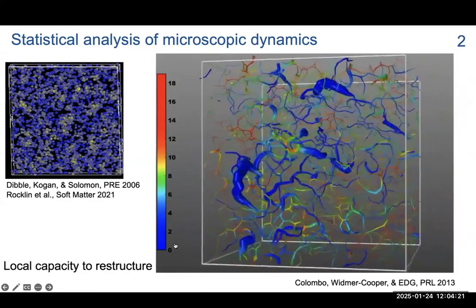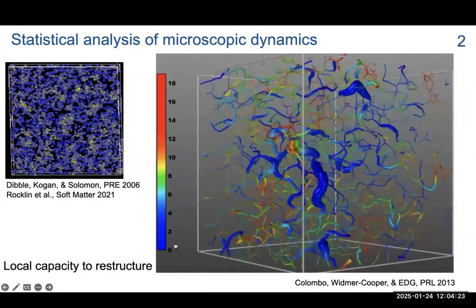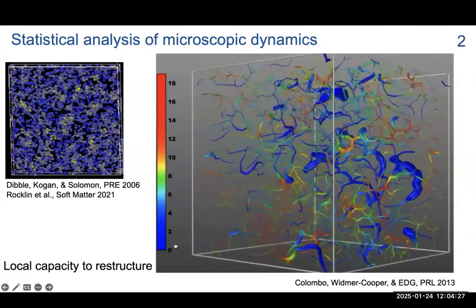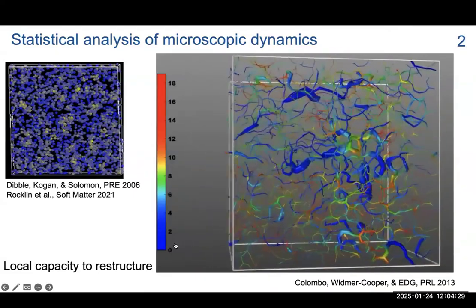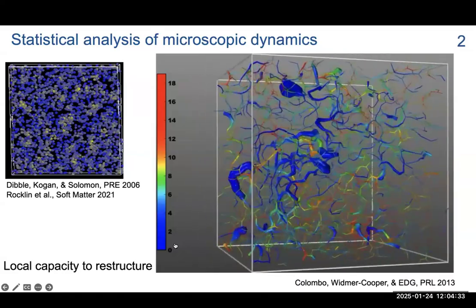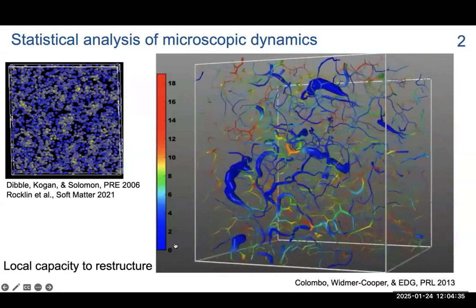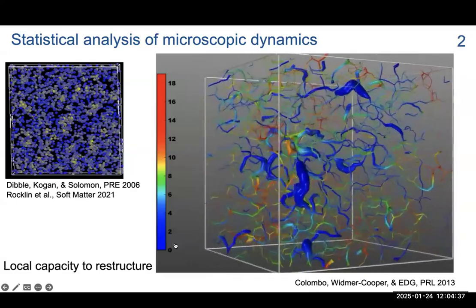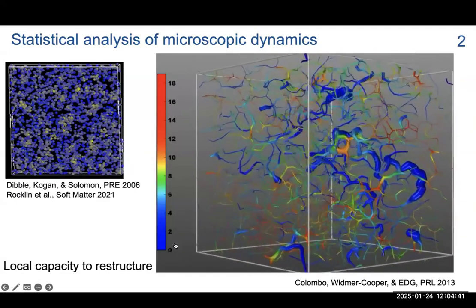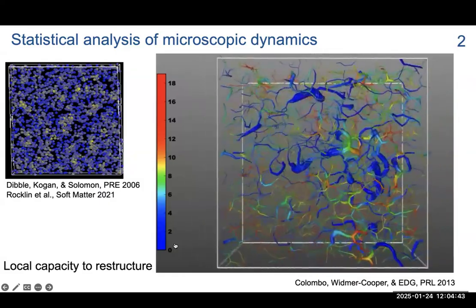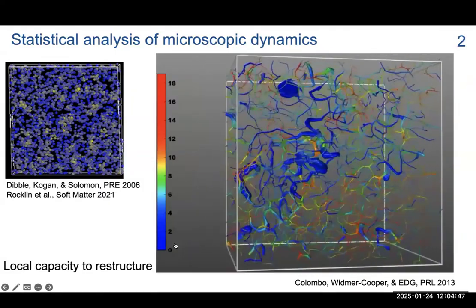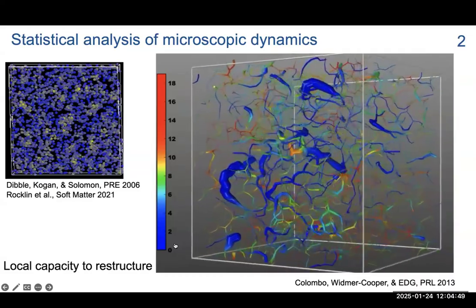That tells me that you break things where they're red, but then the motion propagates away from that into the regions that are floppier, because that's where I can accommodate more rearrangement. And because of the network connections, I can actually go very far away from that. So that's how the idea that you can get hierarchies of timescales and length scales in this system becomes more visual.